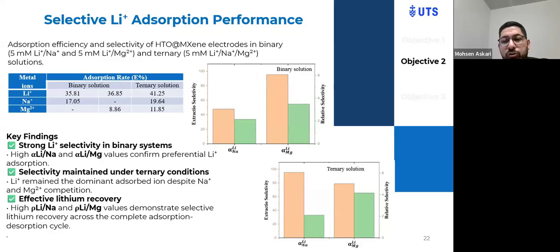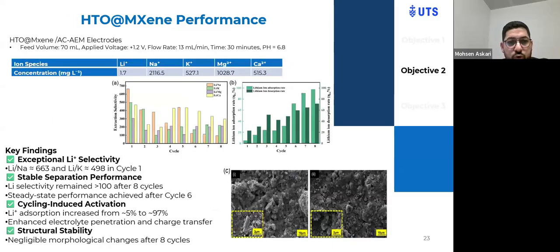In binary and ternary solutions of lithium, sodium, and magnesium, each 5 millimolar, it was tested, and the result shows the preferential adsorption of lithium over the other ions in binary and, more importantly, in ternary solutions. The high selectivity of lithium over these two ions demonstrated the selective lithium recovery across the complete adsorption and desorption cycle. We used here formulas for extraction selectivity and relative selectivity. Relative selectivity is just for adsorption, and extraction selectivity is in adsorption and desorption cycles.